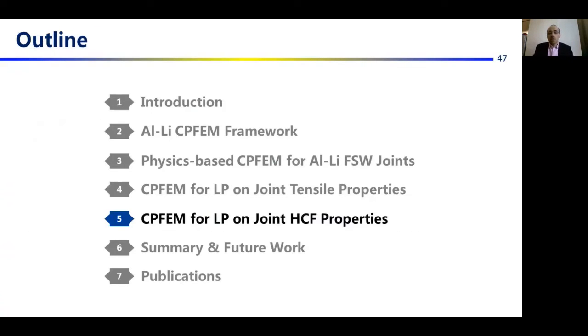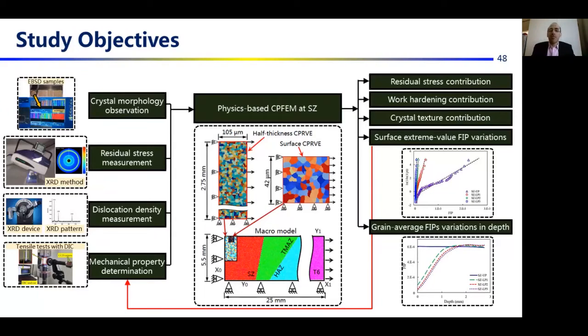Now the CPFEM for laser peening on joint high cycle fatigue properties. In this study, the CPFEM model is developed at SZ, which is the failure location of the fatigue test, by including the microstructure effects such as crystal morphology, residual stresses, and dislocation density. The developed model quantifies the effects of laser peening-induced residual stresses, work hardening, and crystal texture on the variations of extreme value FIP and also grain average FIP values in depth to evaluate the laser peening effects on the joint fatigue properties.